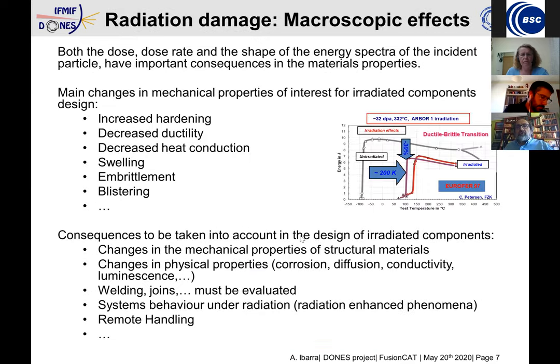Of course, these primary effects have consequences on the macroscopic material properties. I will not go too much into the details of this, but it is obvious that if we change the microstructure of the material, things will happen to the macroscopic properties. And in fact, it has been measured, not only in the case of fusion but in many other areas in which we have radiation, that there is increased hardening, a decrease of the ductility, a decrease of the heat conduction, a change in the swelling, and so on and so on. Many different properties change.